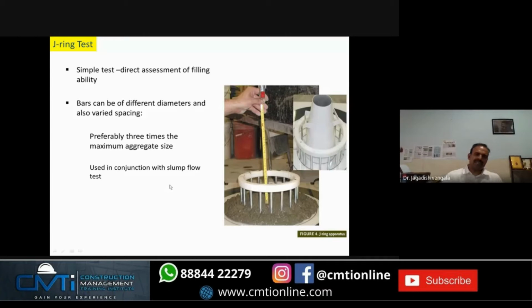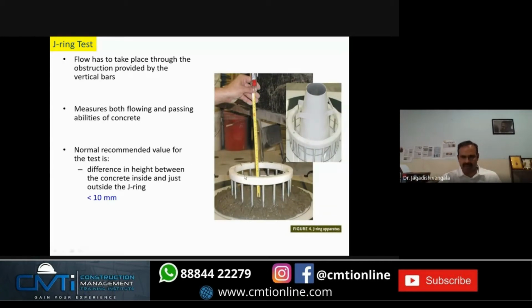And then there is another simple test which is called the J-ring test. The J-ring test is a combination of a ring, and inside the ring you place the Abrams cone, and then you pour the concrete into the Abrams cone. You lift the cone, and then the concrete flows through the J-ring. And then what you measure is the height difference between outside and inside the ring. It should be less than 10 mm. That means it should flow freely even after passing through reinforcement. So here also you measure the passing ability.